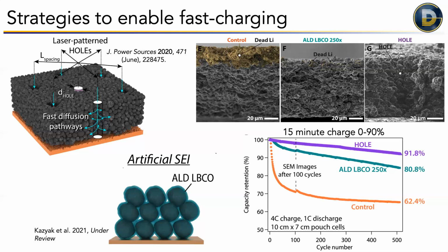So neither of these, the hole or this artificial SEI, actually reduce the energy density of the battery at all. They just decrease the charging time by increasing the charging rate.